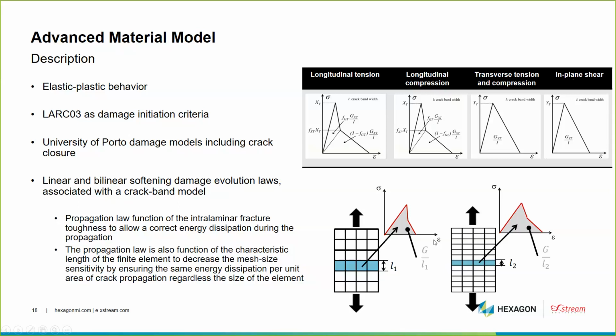Those propagation laws are defined as a function of the intralaminar fracture toughness to correctly reproduce the energy dissipation during the propagation of the damage. But those propagation laws are also a function of the characteristic length of the finite element to decrease the mesh size sensitivity, making sure that we have the same quantity of energy dissipated per unit area of crack propagation, no matter the size of the element. So typically that's the crack band model. It means that the area under the propagation law is connected in some way to the area or to the volume of the finite element.